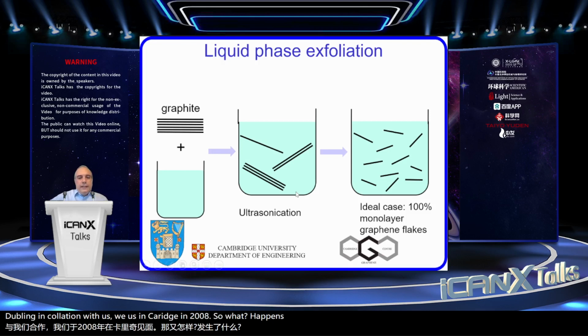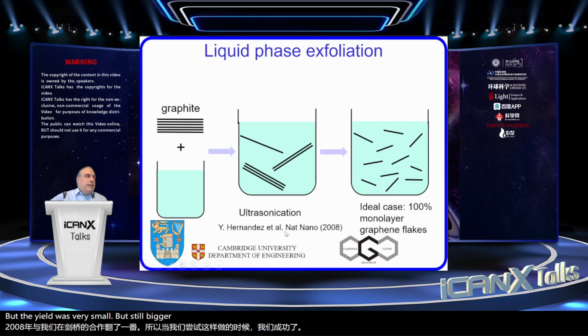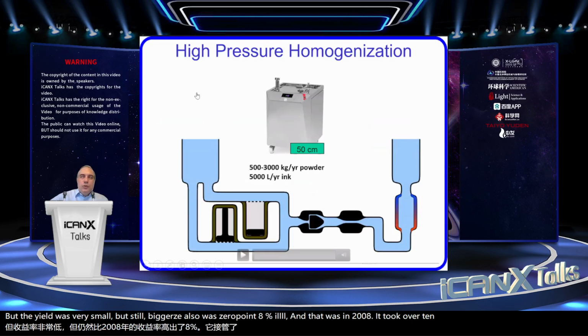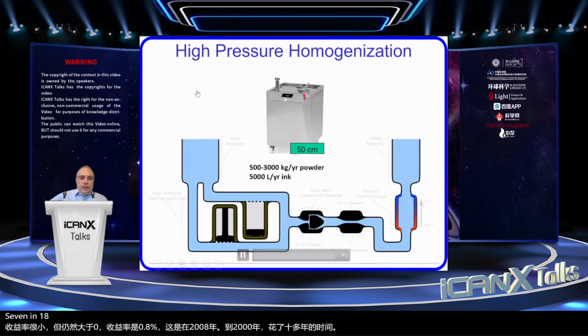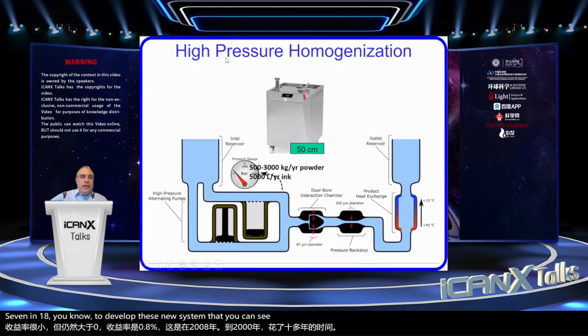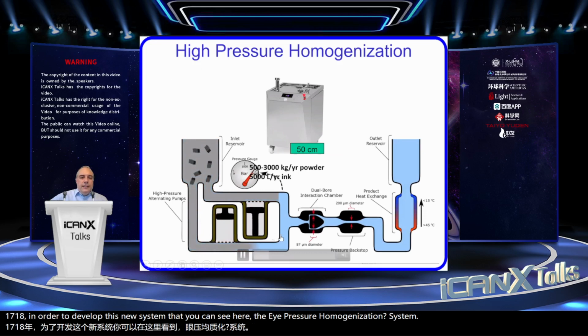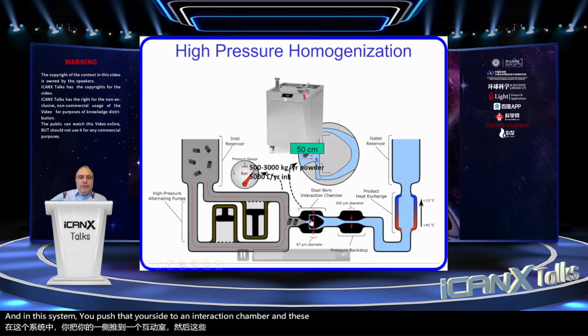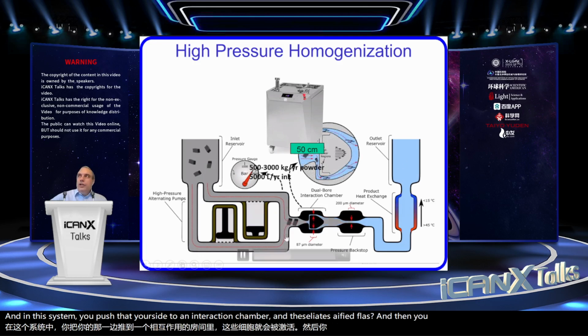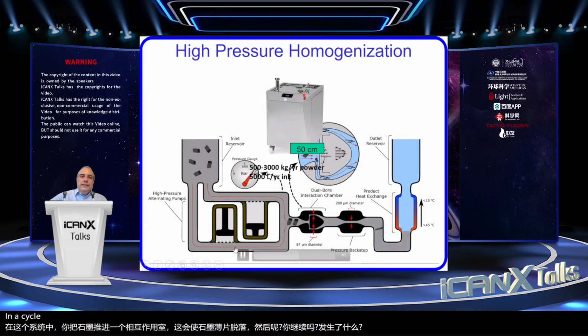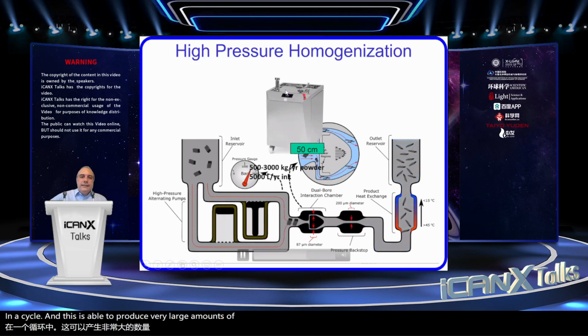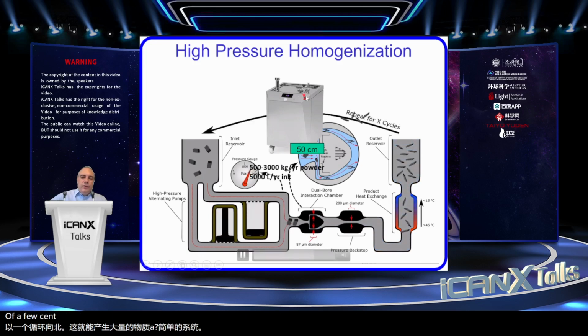So what happened is that when we tried to do this, we were successful, but the yield was very small, but still bigger than zero. It was 0.8% yield. And that was in 2008. It took over 10 years, up to 2017, 18, in order to develop this new system that you can see here, the high pressure homogenization system. In this system, you push the graphite to an interaction chamber, and this exfoliates the graphite flakes, and then you continue going on and off in a cycle. And this is able to produce very large amounts of material. A simple system of 1 meter times 1 meter can produce almost 5,000 liters per year of ink.